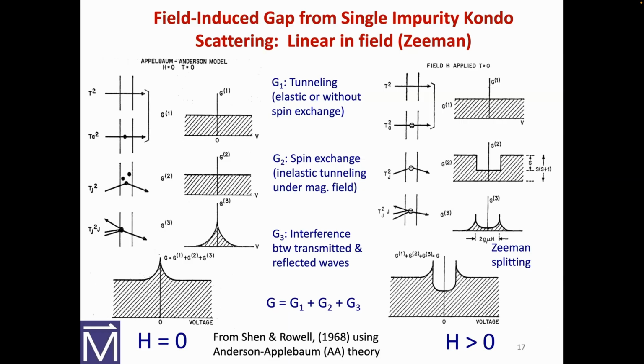Now, if we put a magnetic impurity in the center, remember, tunneling, an impurity in a junction opens up a channel, so it makes things easier to get through. But it's not like optical that absorbs. So what we see is, if we have a magnetic impurity somewhere in the barrier and we apply a field, and we apply a bias, if we give enough bias to flip the spin, then we have an increase in the conductance once you give it enough bias to flip the spin. So you can have this inelastic tunneling through a spin in the barrier.